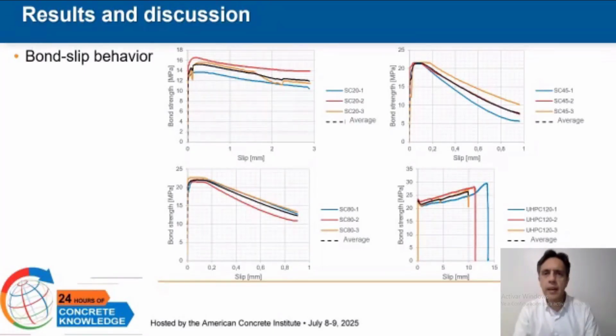As expected, the SC20 mixture exhibits a soft ascending curve with a lower peak bond stress followed by gradual slippage. This reflects limited confinement and weaker matrix resistance. The SC45 and SC80 mixtures demonstrate higher bond strength and stiffer responses. Their curves rise more steeply, reaching higher peak values before dropping abruptly, indicative of partial interface failure.